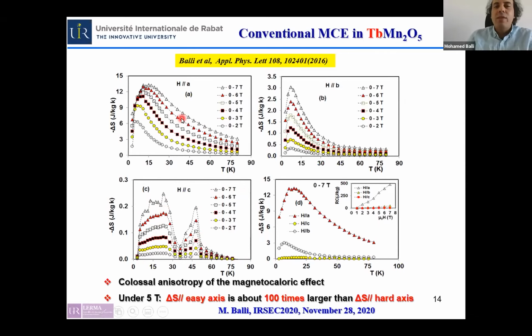This difference in the magnetocaloric effect between the terbium and the aluminum compound can be mainly attributed to the difference in the magnetic behavior of their magnetic moments. In terbium manganese, the magnetic moment presents a ferromagnetic-like behavior, while in the aluminum compound, these magnetic moments present a paramagnetic-like magnetic behavior.